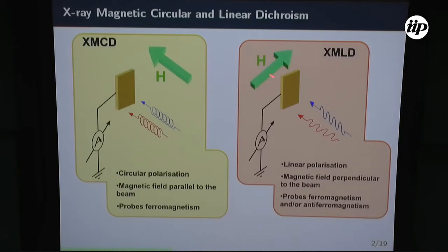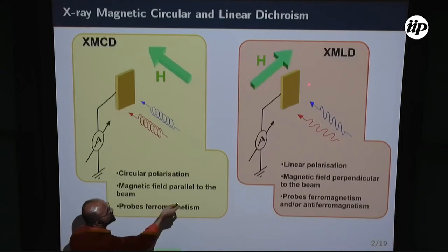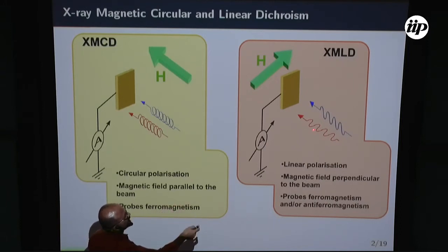But there's another kind of dichroism, the linear dichroism. This is the most direct, the most usual, the easiest to understand. What X-ray absorption probes is the electronic structure of your material. If your electronic structure is anisotropic, your absorption will be anisotropic. So it will be different for vertical or for horizontal polarization. And this anisotropy can be made, for example, if you apply a magnetic field perpendicular, in this case, to the X-ray beam. In this case, the horizontal will probe something different from the vertical.